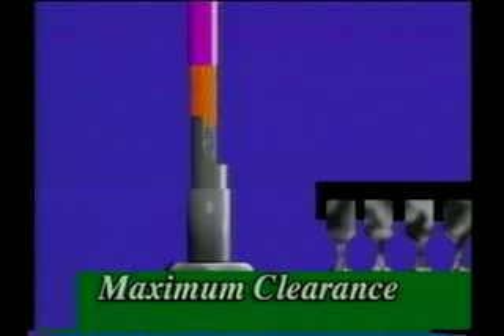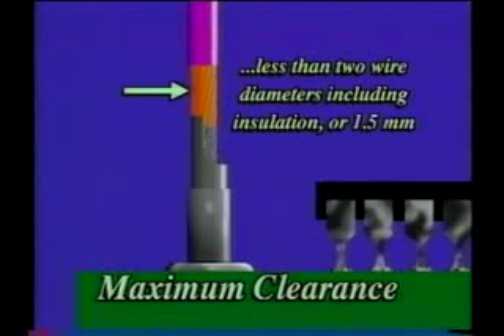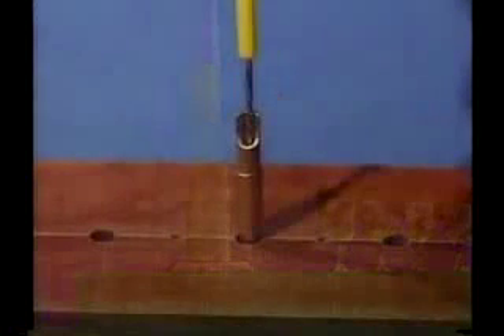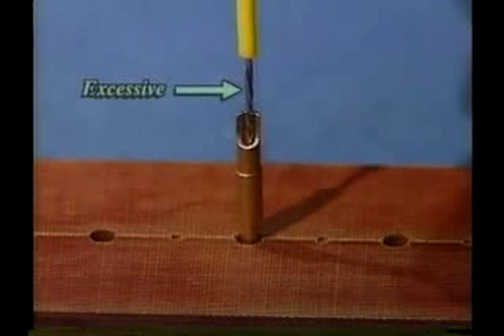Maximum insulation clearance should be less than 2 wire diameters, including insulation, or 1.5 millimeters, whichever is larger, but shouldn't permit shorting between adjacent conductors. In this case, the insulation clearance is excessive and should be corrected.